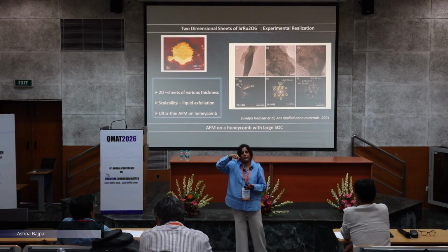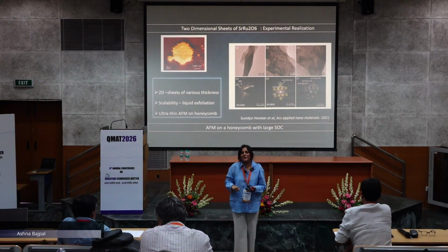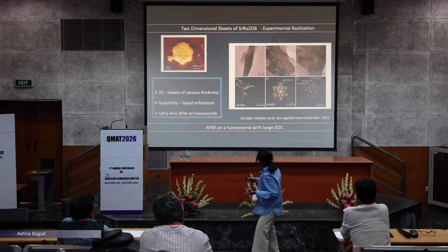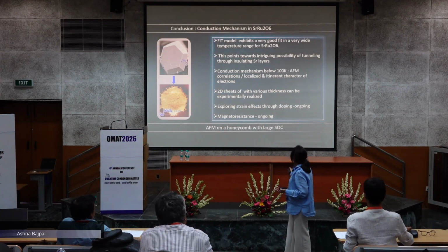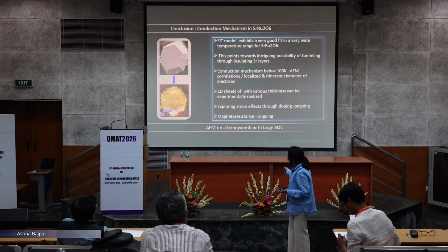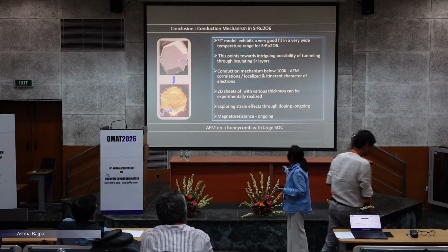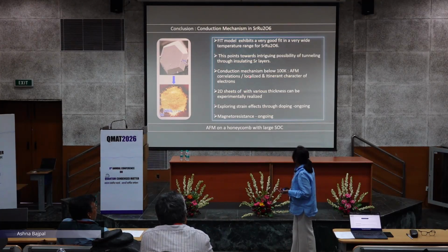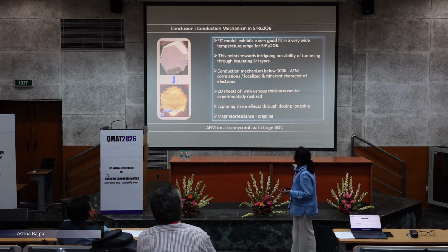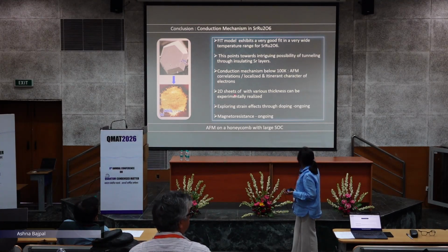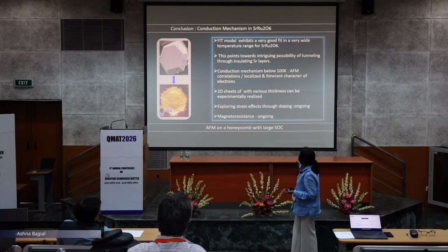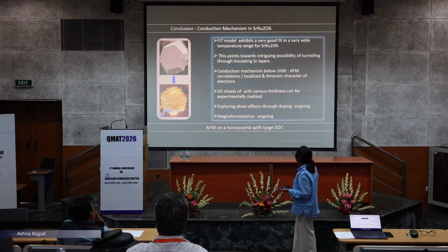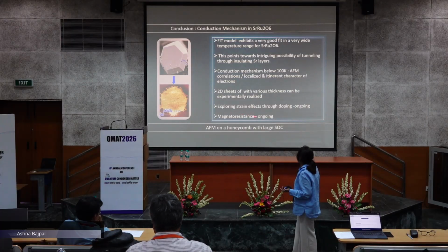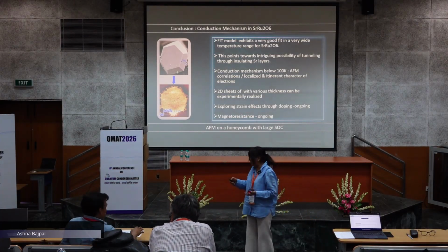It is really non-trivial to measure magnetization in such a system, but hopefully one day we will be able to achieve it, Yogesh. So this is finally my conclusion. We have come from this bulk hexagonal nice looking crystal to corresponding 2D sheets, and we found that thermal fluctuation induced tunneling appears to be a very good model for this system. This also points towards the very intriguing possibility of tunneling through conducting Ru planes through insulating Sr layers. We have realized the 2D sheets with various thickness experimentally, and we are exploring strain effects through doping, which is ongoing, and magnetoresistance measurement and so on.